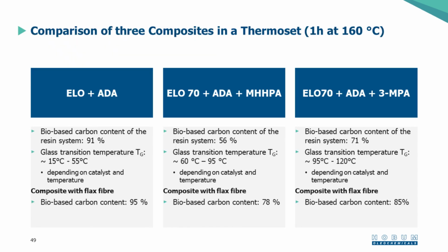So if we compare what can be achieved with truly bio-based materials here, if you just mix ELO with artemisinic acid, you will have a bio-based carbon content of the resin system of 91%. But the glass transition temperature you will reach, depending on catalyst and temperature that you apply in the curing, is 15 to 55. In some applications, that might even be enough. For most of the applications that we're talking about, it is not enough. Of course, the composite with flax fiber will then have a bio-based carbon content of 95%.